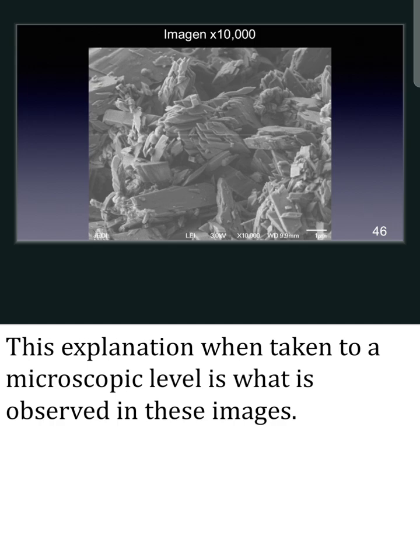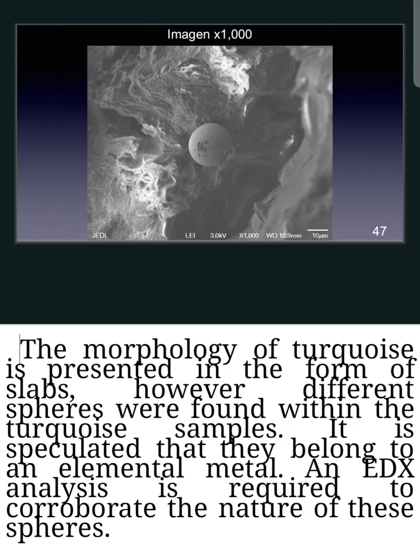This explanation, when taken to a microscopic level, is what is observed in these images. The morphology of turquoise is presented in the form of slabs. However, different spheres were found within the turquoise samples. It is speculated that they belong to an elemental metal. An EDX analysis is required to corroborate the nature of these spheres.